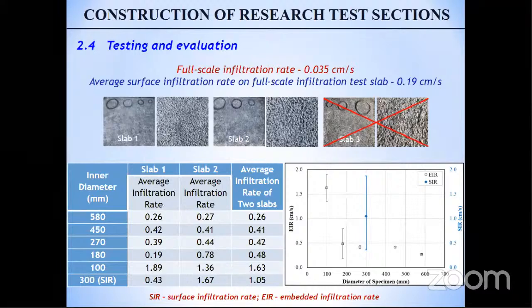Now, amongst 3 test slabs, it was found out that one of the test slabs was clogged. So for final results, the readings of only 2 slabs were presented, and it was observed that the infiltration rate tended to decrease with the increasing size of the specimen, and the ring diameter of about 300 mm actually gave us the true infiltration behavior of that of a full scale pervious concrete slab. Now, this 300 mm diameter that we observed is actually close to the ASTM infiltration ring diameter, which is also close to 300 mm.